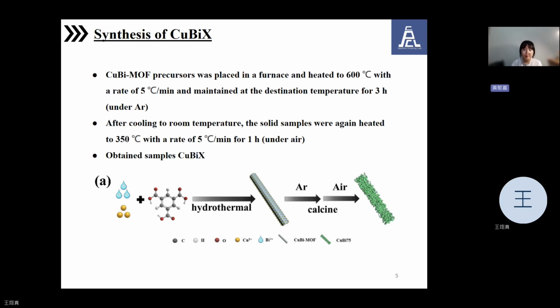The rod-like CuBi MOF precursor was synthesized via the one-step hydrothermal method that we mentioned on the previous page. This precursor was then carbonized under argon at 600 degrees Celsius and oxidized in air at 350 degrees Celsius. Finally, we can obtain the samples, and the sample proportion can be adjusted by the amounts of copper nitrate trihydrate and bismuth nitrate pentahydrate.